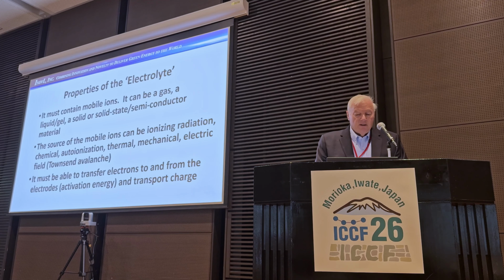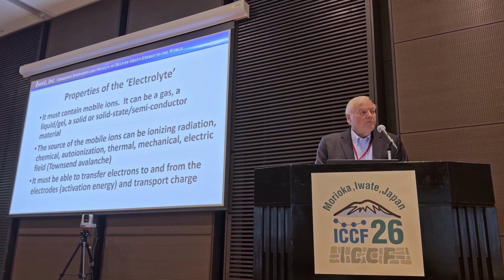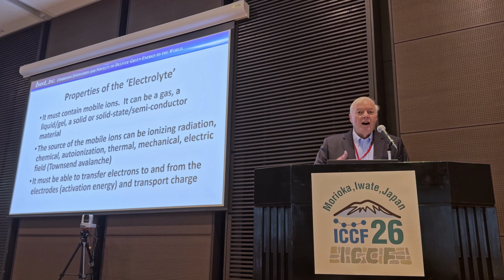You have the activation energies and the transport. This is another point. We talk about activation energies. That's the activation energy for the system, which involves not only the palladium hydrogen electrode, but also the counter electrode. And so we're now beginning to focus on the low work function electrode and make sure that that's not limiting the activation energy or how much current we can pass.